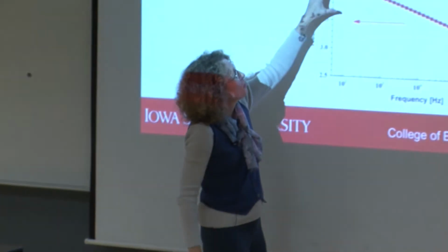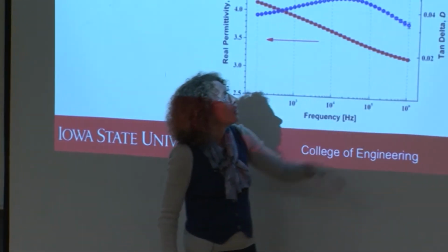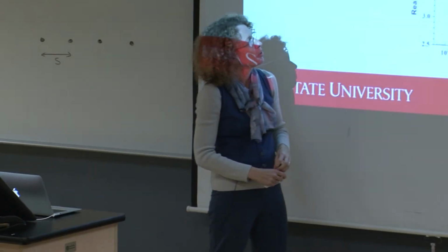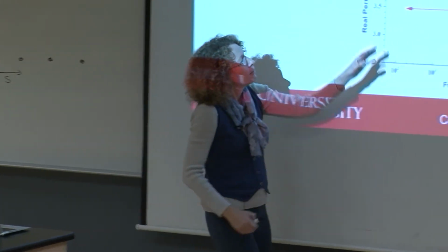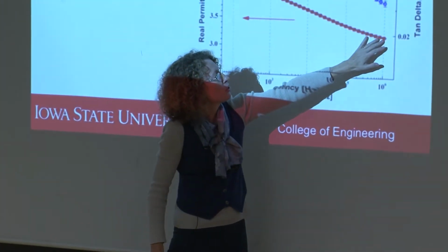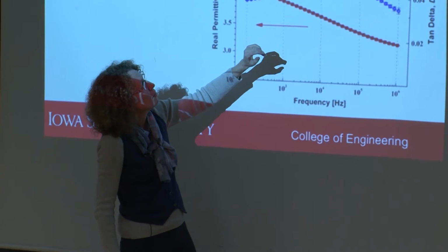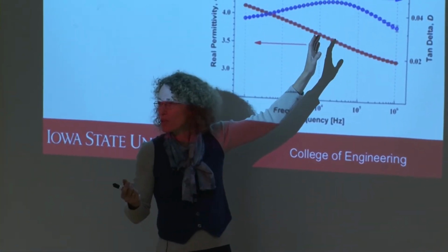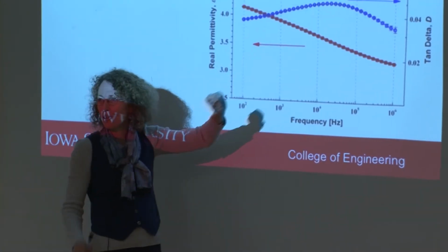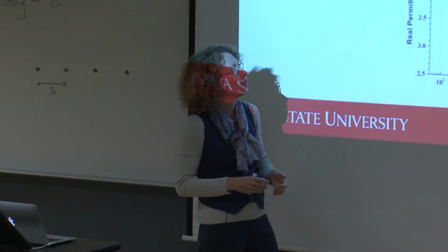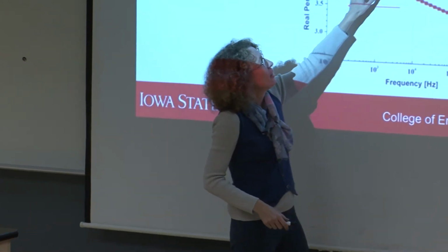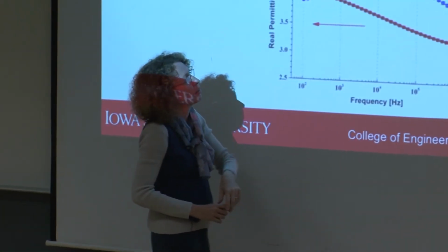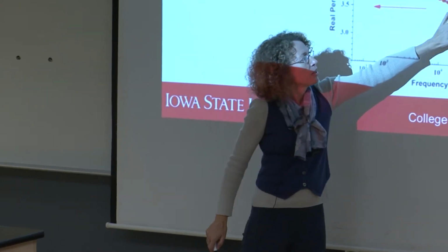And this is what the spectrum of nylon looks like as a permittivity measurement. As you can see, it changes as a function of frequency. The reason for that is that the material response is slowing down. It's finding it hard to keep up with that applied field change. And then the imaginary part has a peak in it corresponding to the drop here.